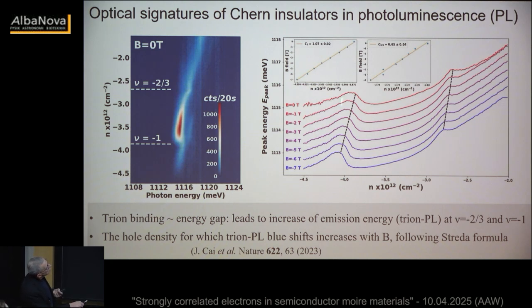And we follow this with magnetic field, and in these you find that the slope here is 0.65, here it's 1.07, which is most likely due to the fact that we don't have as well-defined a cusp as in this one. So this is a remarkable state, right? In the sense that it's a topologically ordered state showing up at zero magnetic field. It's the counterpart of fractional quantum Hall states.